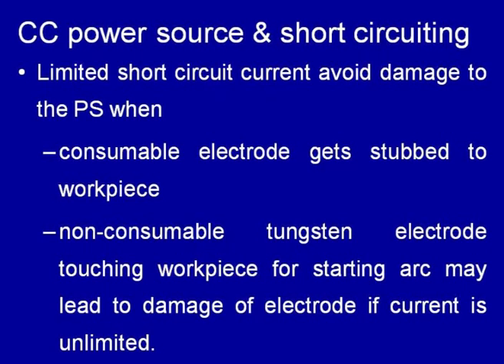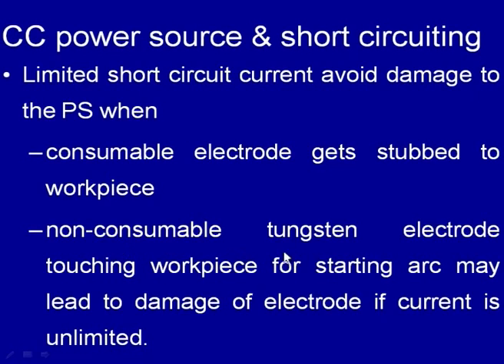This can happen when the consumable electrode gets stuck to the workpiece, or when a non-consumable electrode like tungsten is brought in contact with the workpiece for starting the arc, and this can damage the electrode if a very high flow of current starts. Especially when working with the GTA welding process, it is desired that the heat generated while igniting the welding arc is not much, but a sufficient number of electrons are generated so that the arc can be initiated easily without causing much damage to the electrode tip.